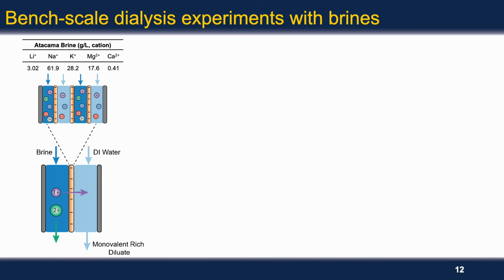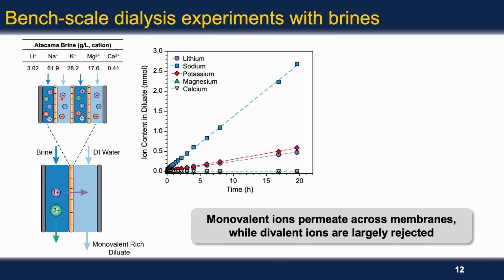For the last part of our study, we tested this separation process in a more practical system, where we used the model Atacama brine as our feed solution, and we used the flowing electrodialysis stack with only negatively charged membranes and without the application of an electric field. In these experiments, we found that the monovalent ions readily permeate across the membrane, but the divalent ions are largely rejected, just like in our more controlled experiments.